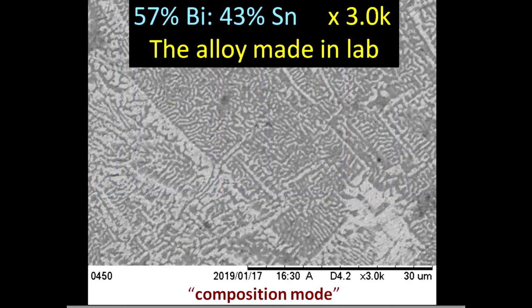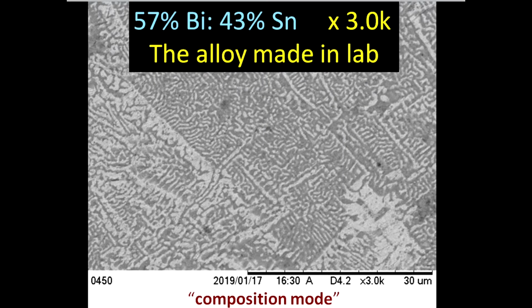So this is the alloy that was made in the lab, 57% bismuth and 43% tin. This composition has a very special, kind of funky name. It's called a eutectic, and that is the lowest melting point composition. When we looked at the other composition, about 67% bismuth and 33% tin, that would have had a different melting point than the one we looked at in this particular lab, and it's higher. This particular composition has the lowest melting point of any composition of bismuth and tin.